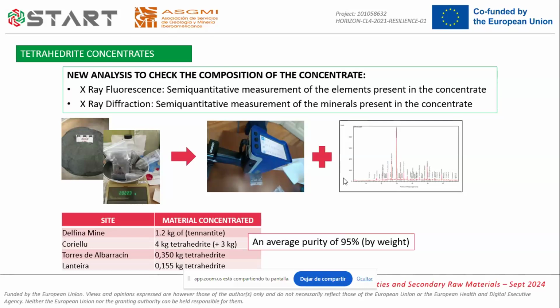So what we finally got was 1.2 kilograms of the concentrate of tetrahedrite in Delfina mine, 4 kilograms in Coriellu mine, plus other 3 kilograms that was processed in a second sampling campaign. We collected 350 grams in Torres de Albarracín and 155 grams in Lanteira. All of these concentrates have a purity of at least 95% of tetrahedrite.